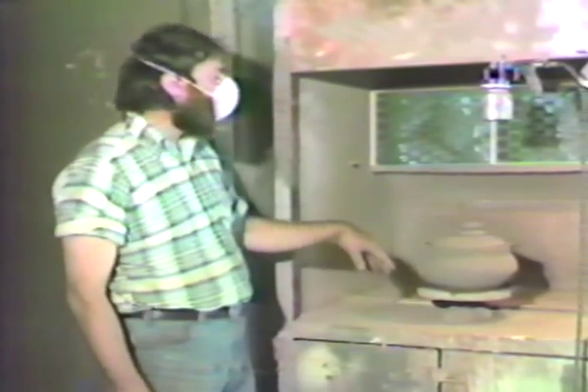And a lot of the glazes are funny. If you have a thicker coat of glaze, it may turn the glaze lighter. Some glazes may turn darker with a thicker coat. And XB Blue will actually go from a light brown to a dark blue and then back to a light blue. All one glaze, but just depending on the thickness. So if you want to get a nice even coat, spray up and down a few times. Maybe spray 7 or 8 thin coats rather than trying to get one heavy coat, because one heavy coat will cause you more trouble than it's worth.